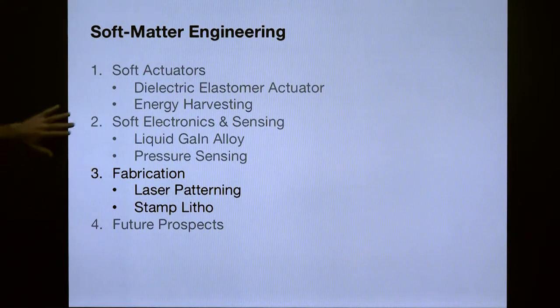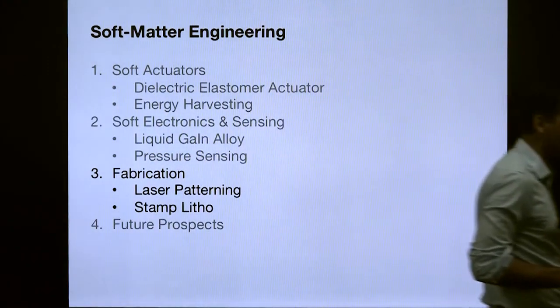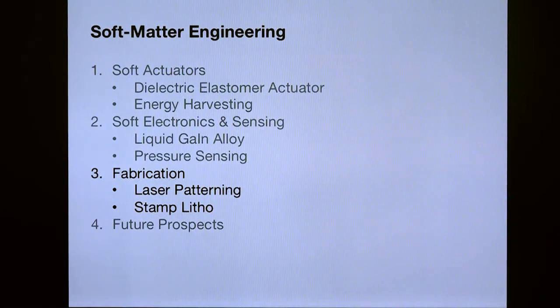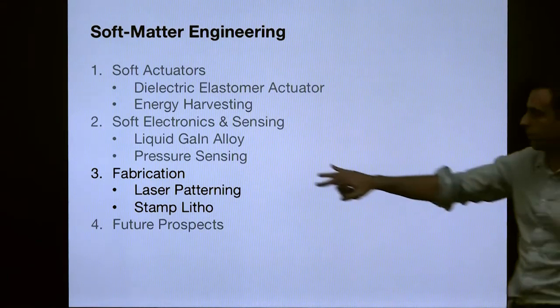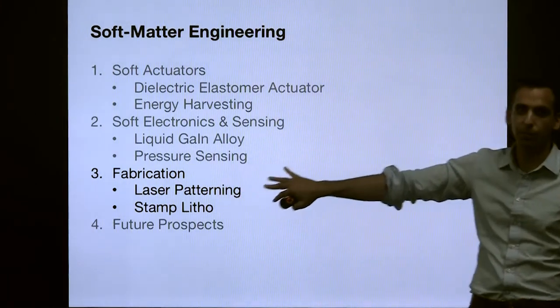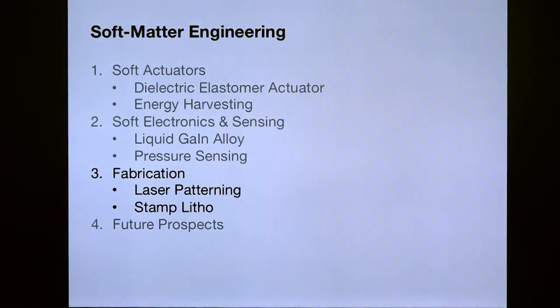The principle here is fairly simple: we can dip a stamp and transfer patterns to another surface. Here it's a single dip into a pool of our liquid metal, and using the Cartesian droplet printer to deposit droplets on the surface. We deposit the droplets close enough to form lines, and then freeze this and seal it up.